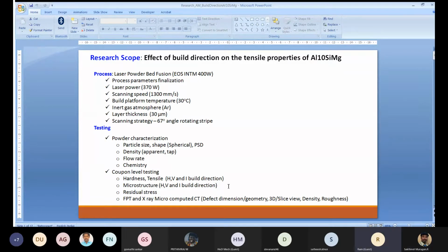Thank you. And flow rate, that is on testing. Third point, if you see the flow rate, we use the Hall flow meter to measure the flow rate: 50 grams of powder to flow through an orifice of 2.5 mm in the Hall flow meter. How long will it take? That is nothing but the flow rate, in seconds for 50 grams. How many seconds does it take for the 50 grams to flow through it?